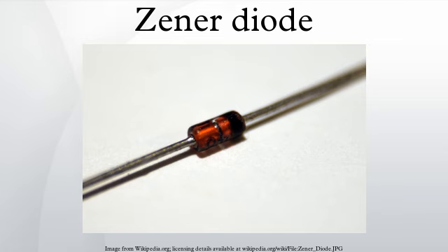The emitter-base Zener diodes can handle only smaller currents as the energy is dissipated in the base depletion region, which is very small. Higher amount of dissipated energy causes thermal damage to the junction and/or its contacts. Partial damage of the junction can shift its Zener voltage. Total destruction of the Zener junction by overheating it and causing migration of metallization across the junction can be used intentionally as a Zener zap antifuse.